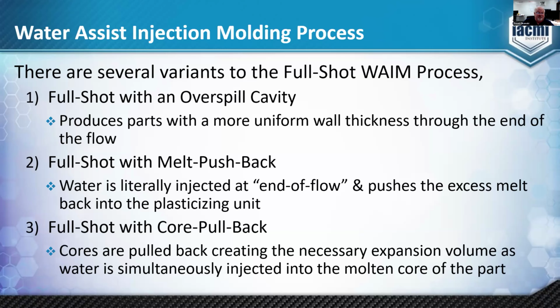You can also have a melt pushback method where the water is injected literally at the end of the flow, and it pushes the excess melt back into the plasticizing unit. You can use this technique if your polymer melt is hydrophobic, right? In the case of nylons, where it likes water, you really wouldn't want to do this type of process. And you can also do a full shot with a core pullback. So as the polymer melt fills the cavity, you can actually release the cores and pull them back, and that will create the volume for the water to be injected and expand and hollow out the cores.